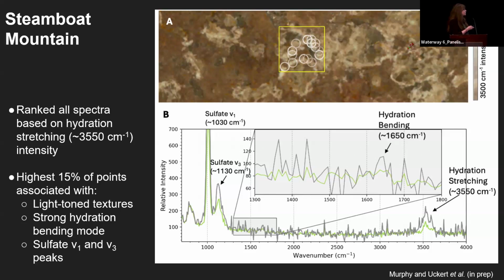So that average spectra that I showed in the previous slide is in the green, and our comparison in the gray are represented from these spots. And this is showing that it pulls out a more intense hydration feature here and the sulfate feature compared to the average. And it's correlated to these wider rims. So this is showing us that we can pull out some textural information to see where that sulfate is within the map.